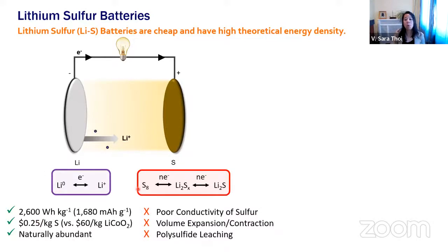One being that sulfur is a poor conductor of electrons. And so getting that first set of electrons into sulfur has a really high activation energy. Sulfur also undergoes volume expansion and contraction that leads to pulverization and mechanical instability. And the one problem that we're going to focus on today is the generation of these lithium polysulfides. As it turns out, lithium polysulfides are quite soluble in most conventional liquid electrolytes. And when that happens, the lithium polysulfides can leach from the sulfur electrode. And then when we go back to charge our battery, we could end up reducing the lithium polysulfide into lithium sulfide on the wrong electrode. This can then cycle back and forth in what is called the polysulfide shuttle.